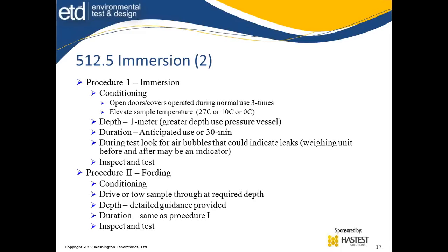During the test, look for air bubbles that can indicate leaks. Also, potentially weighing the unit before and after could be an indicator that something happened internally. Do the inspection and the test. Again, like we said on one of the other items, be conscious of the pass-fail criteria. How much is allowed to come into it? Okay. If it goes under for 30 minutes and there's a minimal incursion, if that's an acceptable condition, this needs to be decided before the failure occurs, and we're negotiating to see if it's going to be acceptable. So come up with an idea of what is the pass-fail.